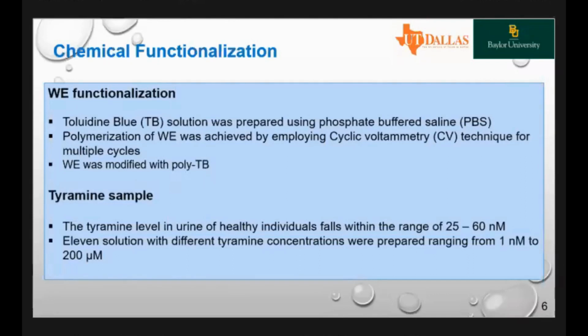To functionalize the working electrode, we put the toluidine blue (TB) solution. It was prepared in PBS, and then the polymerization on the working electrode was achieved by employing the cyclic voltammetry technique for multiple cycles, about 20 or so cycles, and it is well polymerized and works quite well. So the working electrode was modified with toluidine blue, and that is the key component right here.